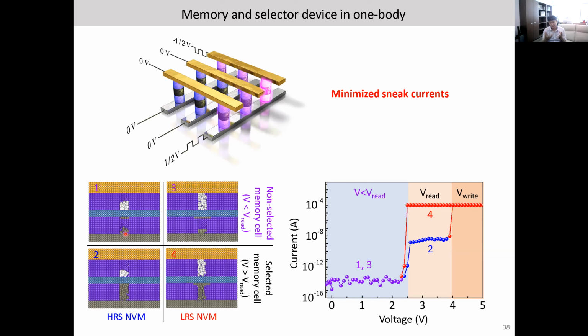Of course, this has been suggested as RRAM, but the instability was the problem. We maximized this problem. As soon as we turn off the voltage, this silver is broken. So this can be considered volatile memory, or in our study, we used it as a selector. To maximize this instability, we used a little bit thicker hBN so that this instability is more developed. We want to make totally unstable RRAM because we want a volatile memory for the selector.